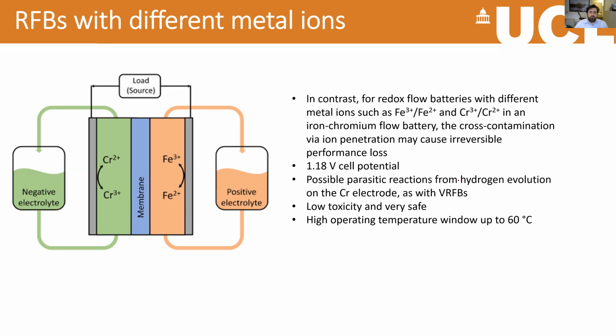That can also cause issues of side reactions and other deposition, for example, of solid precipitates within the flow battery, and that can cause problems as well. Additionally, we could have these issues of solubility and therefore concentration coming out by changes in temperature as well, and that could cause deposition or loss of material as well. So in those cases, eventually we would have to regenerate or replace the electrolyte.